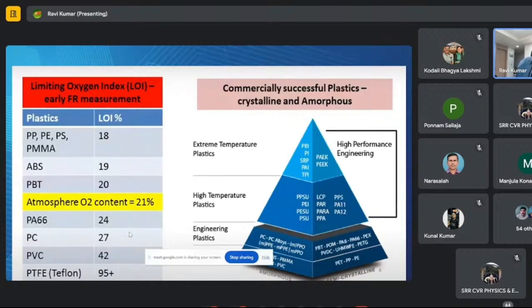PA66 shows an LOI of 24, polycarbonate is 27, PVC is 42. PTFE, commercially known as Teflon, shows the maximum LOI, 95%. So Teflon cannot catch fire because oxygen cannot penetrate into the PTFE material. This is the toughest material, and it can survive in the humankind. But the problem is that PTFE is very costly. We cannot buy it for every normal person. So to overcome that, we are developing a nano material. We coat that nano material on different woods, and it can save lives and delay the limiting oxygen or fire catch. Here you can see the commercially successful plastics, crystalline and amorphous materials.